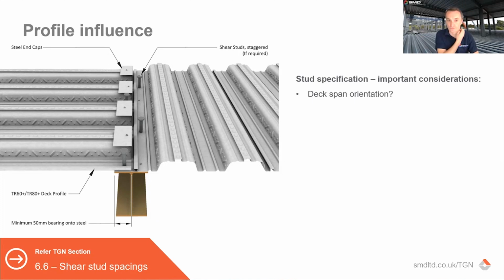On the right, you've then got flexibility of where you can put those studs. So the number that is required is more achievable in this scenario. However, you will have different resistances on different studs. So if you were getting into the complex design of this particular beam, you would have a different resistance here than you would here, because this is more like a primary beam scenario. This is a secondary beam scenario, because the deck is coming into the beam. Just something important to consider. Obviously, beam softwares, etc., will consider a lot of this anyway, but it's important to understand what can be achieved.